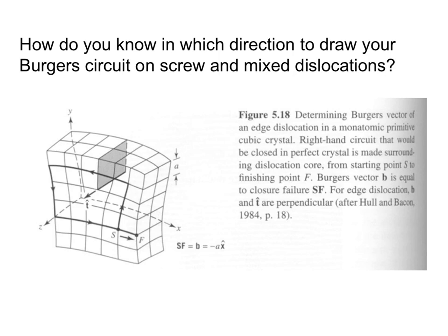So the first important thing is to find the direction of t, which is our dislocation line. And so in this picture, the dislocation line is defined to be coming out of the page. We could have easily defined it to be going into the page, but it's defined coming out of the page. And so we take that as the convention, and then we make a right-handed circuit.